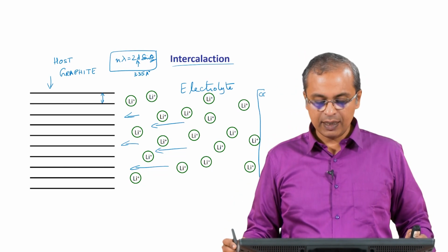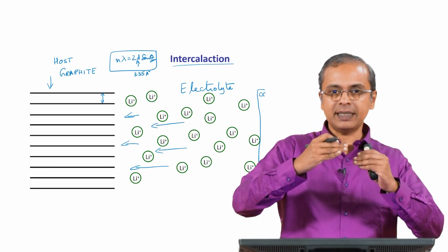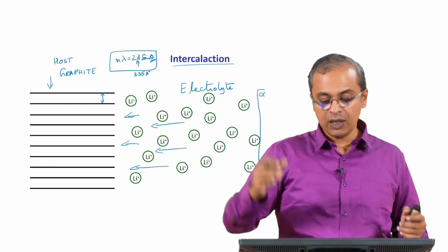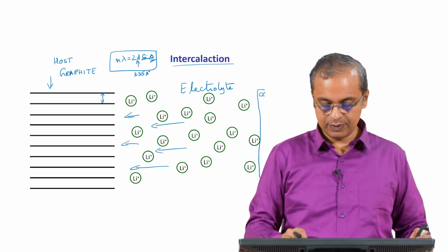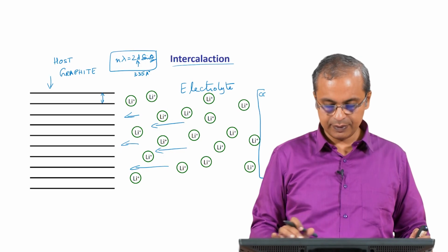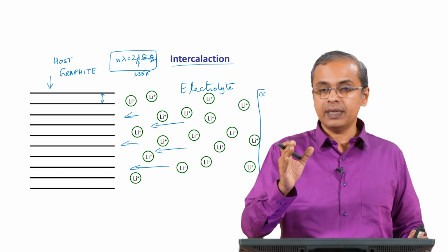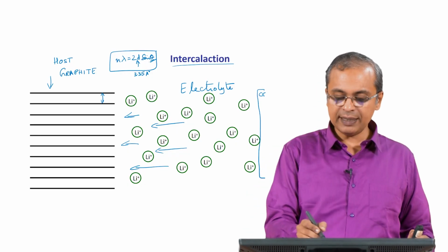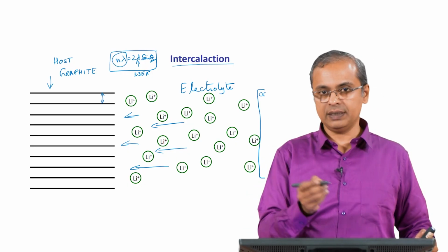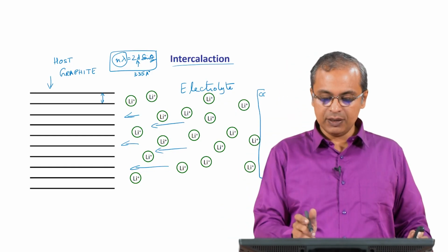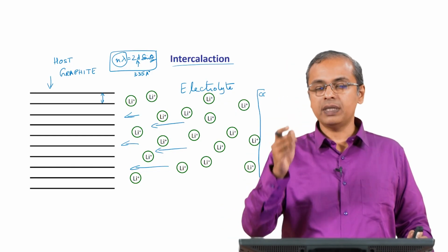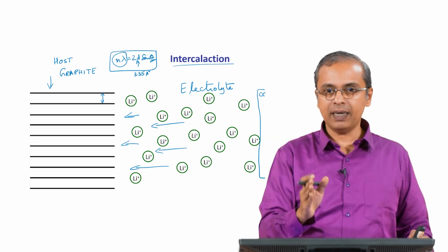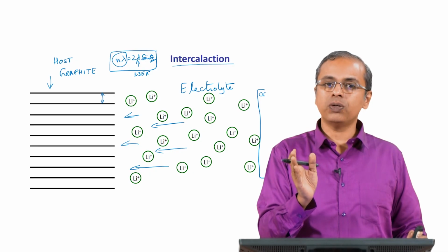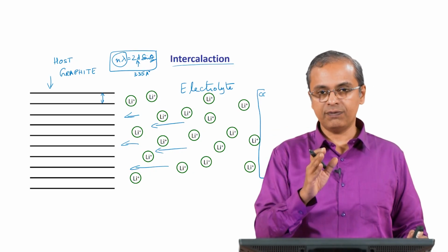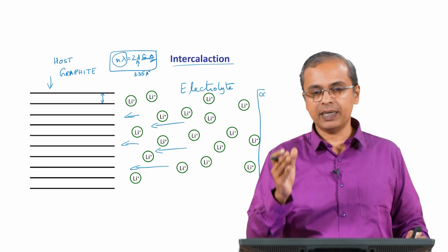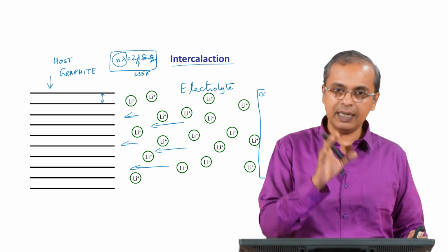If you use a particular value of wavelength, you will get a particular theta at which the peak will show up, right. Now as you put lithium into it, on average the spacing is increasing, so on average the d value is going up. As the d value keeps going up, the theta at which the peak will appear keeps decreasing, because n lambda is a constant, you are using the same wavelength. So, if you keep increasing d, theta has to come down. The angle at which the XRD peak appears will keep shifting to lower values of theta, and you will see the peak appearing at lower and lower values. And in fact, this has clearly been observed.